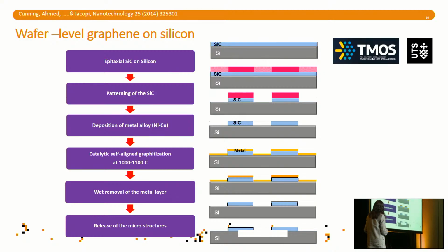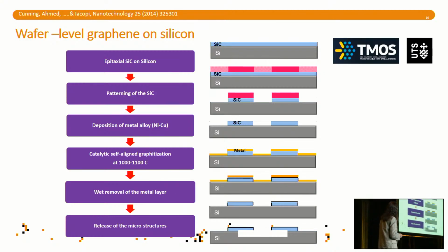I'll show you later. The appealing thing of the platform, as I said, is that it's site selective, meaning we know how to dry etch and pre-pattern the silicon carbide, which is the source for the carbon, on the wafer level through lithography and etching. And then we can just deposit the layers of catalyst as a blanket layer that covers the whole surface of the wafer. And automatically, what will happen is that where you have the source of carbon, you will have graphitization. But everywhere else, where you have only the silicon, you will have silicidation, and the silicides we are able to remove. And when we remove the silicide, with sonication and wet etching, the graphene adheres very, very well to the silicon carbide. So it stays there, which is beautiful.